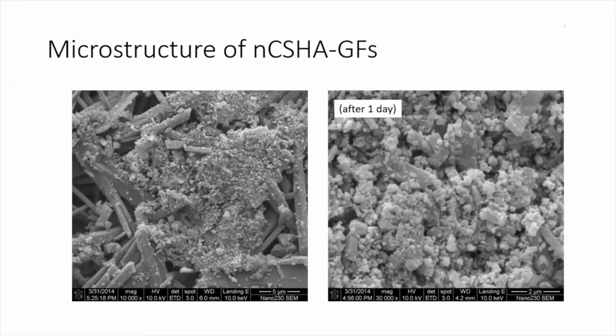From this SEM image, we can see a lot of porous space, and also the crystallization of porous hydroxyapatite covering it. And we put it into the HBSS solution for 1 day. At the right-hand side image, we can see a lot of crystallization structure covering the calcium sulfate. This might be through the dissolution and recrystallization of the nanocrystalline calcium sulfate and the porous hydroxyapatite. This would be beneficial for carrying the growth factor and its release afterward.